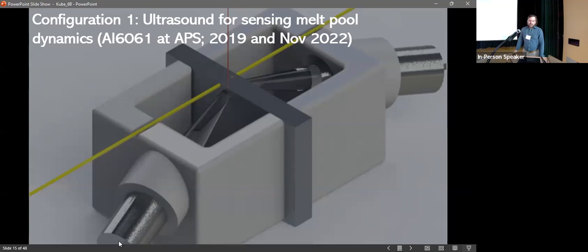I'll be talking about two configurations. The first configuration is for the melt pool monitoring, and this is set up specifically for synchrotron measurements. Here the yellow beam depicts the X-ray that's imaging the cross section of the melt pool.